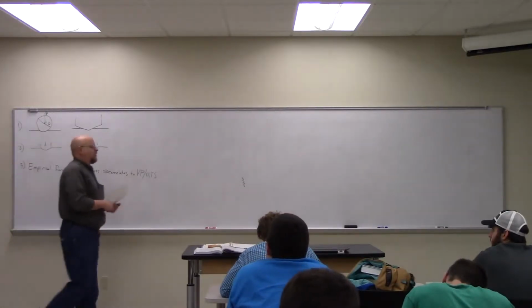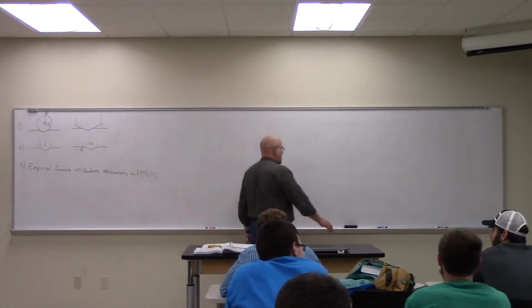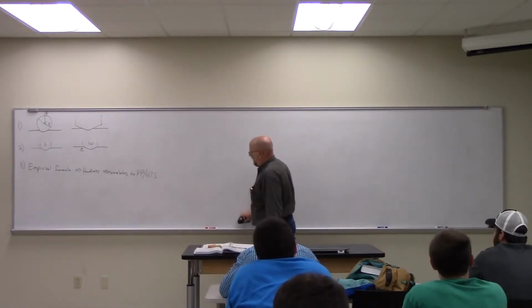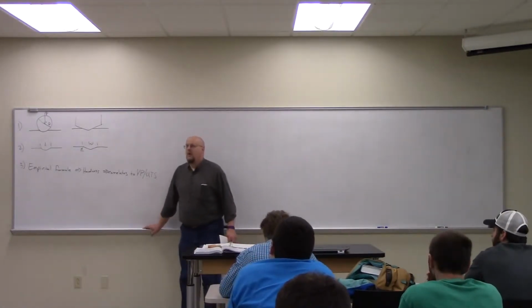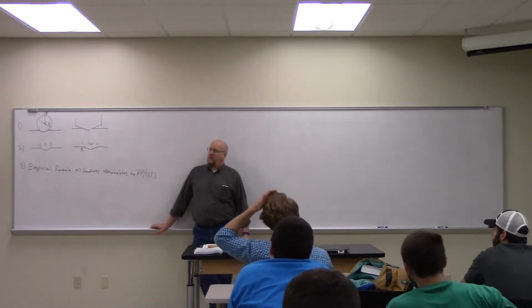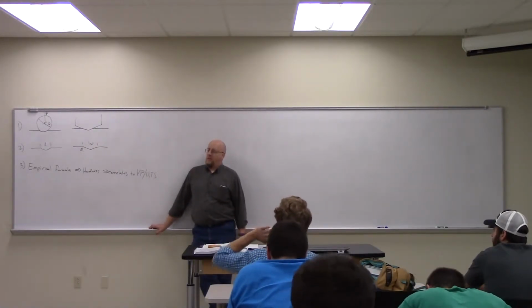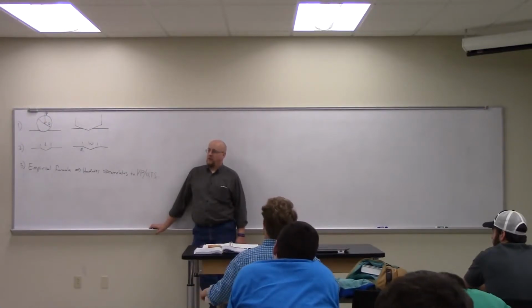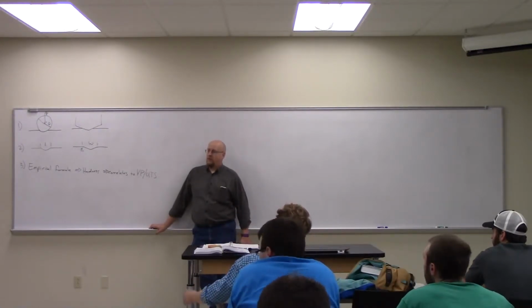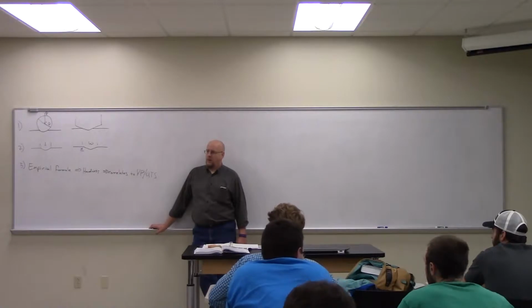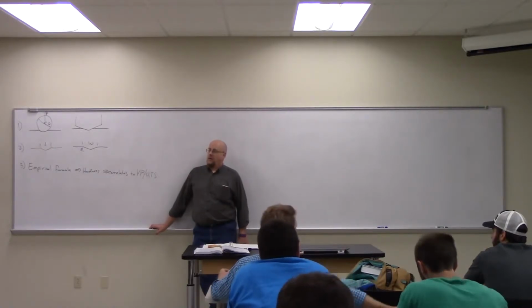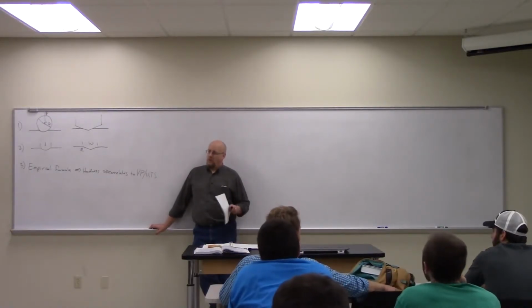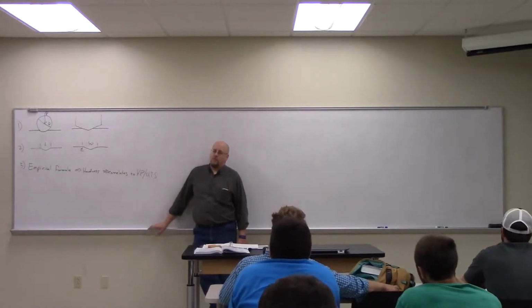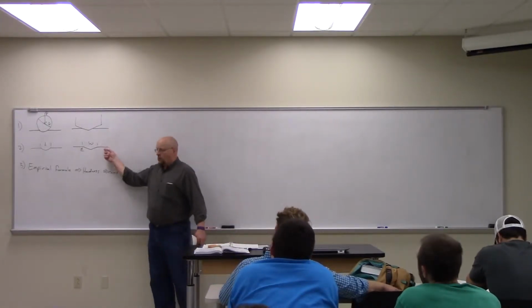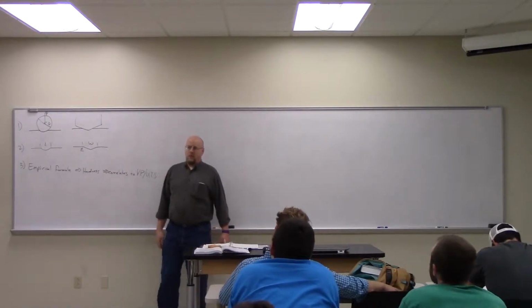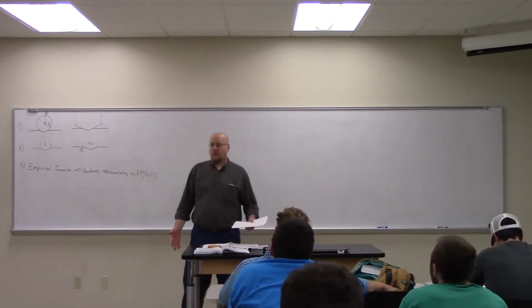You can do it with anything that will deform. You can do it with ceramics, though not all ceramics have enough plasticity to them. There are some tough ceramics that you can do indentations with. Silicon nitride is one. You can measure the properties of silicon nitride by doing little Vickers indents. The problem is that it actually generates little cracks coming out the sides, so it's not really as non-destructive as you'd like it to be.